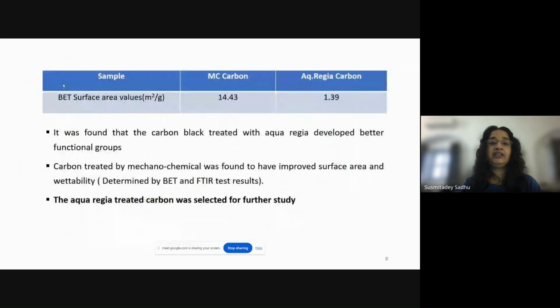On the other hand, if we look at the BET surface area, the BET surface area of the mechanochemically treated carbon black is much higher compared to the aqua regia carbon black. So finally, considering both the factors, we decided to go ahead with the rest of the work with the aqua regia treated carbon black, which has higher surface active groups.